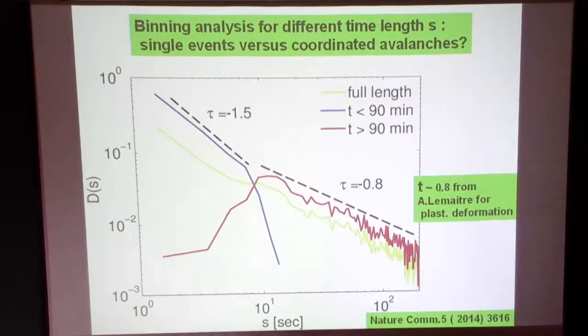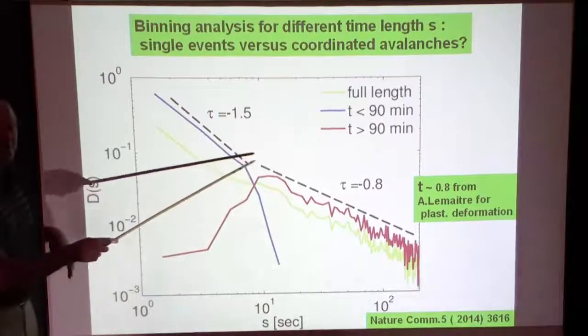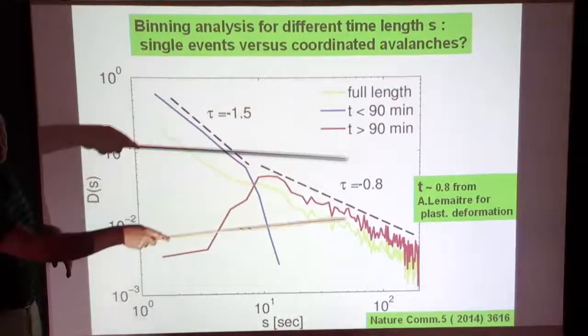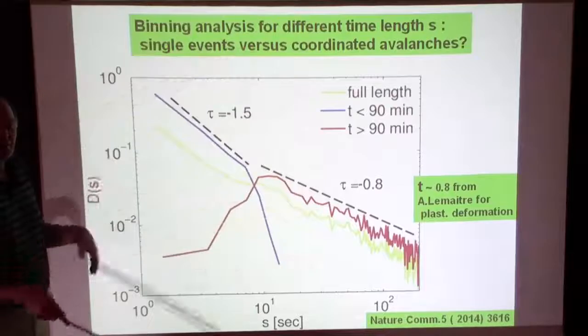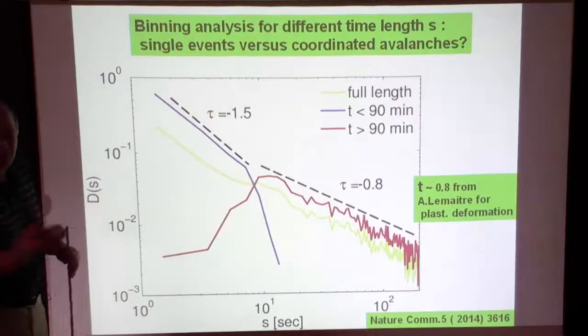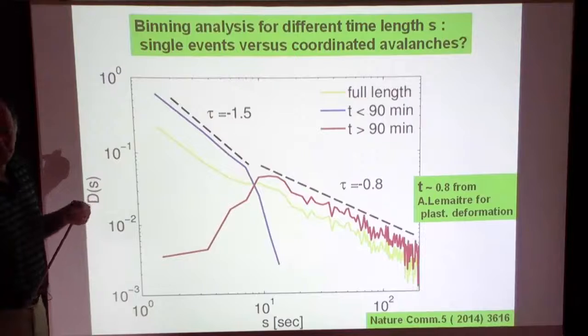So, I mean, you said you're near Tg and you're near the yield stress. Yes. So which one of those matters? Could you go well below Tg and see the same sort of thing? We didn't. If we go well below Tg, we don't see it. That is what the data I showed you before. And do you have insight on how this crossover timescale changes? Okay, we're doing it right now. We try to see whether this scales somehow with the Vogel-Fulcher-Tammann law, this kind of alpha relaxation process. Okay. And how does it change?